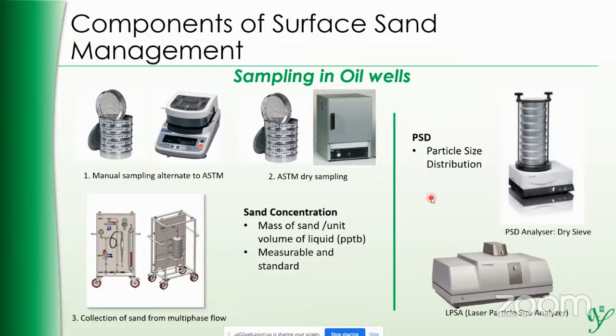Particle size distribution, which Mr. Babu just mentioned in detail, is measured with this equipment. For those who don't know, you take the sand sample here and provide good vibration and shaking to this entire unit. It sieves the sand. These are sieves, or filters, of different sizes, starting with the coarsest at the top and the very fine filtration at the bottom. Once you do that shaking, the entire sand you have given distributes along as per the sizes, and that's where you get the particle size distribution. This is a very conventional way of doing that.